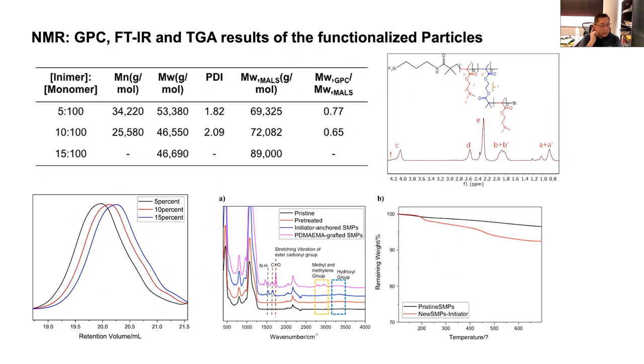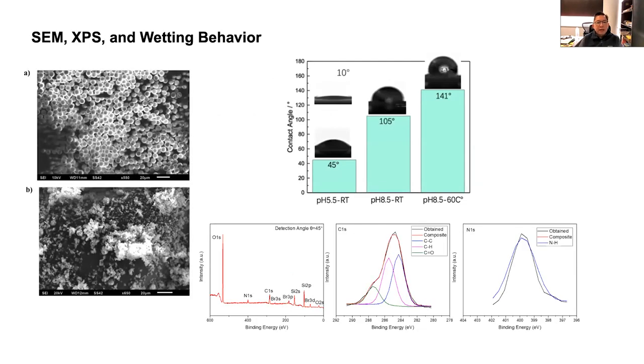And as you can see here, by increasing the amount of the inimer, we essentially control the branching. The higher the inimer, the higher the branching. But we can also control the molecular weight based on that ratio. And both TGA, NMR, and IR prove this work. But probably it's more identifiable if we look at the modification of the particle.